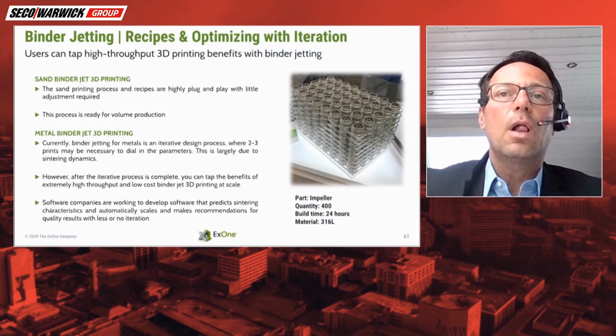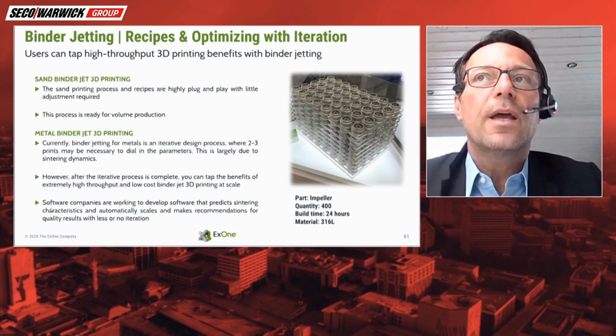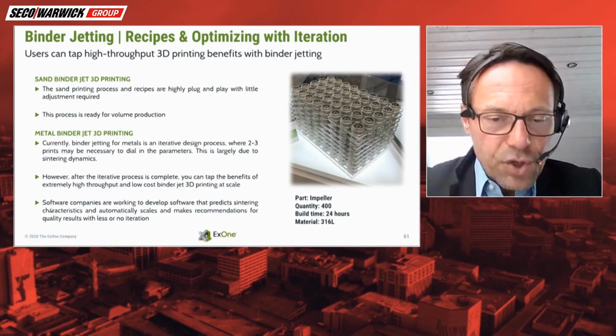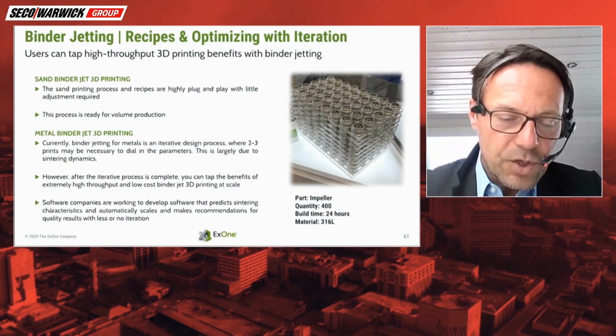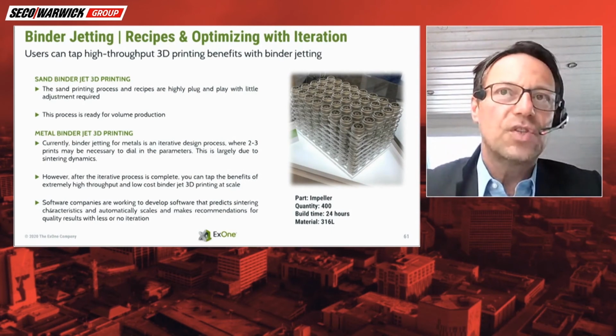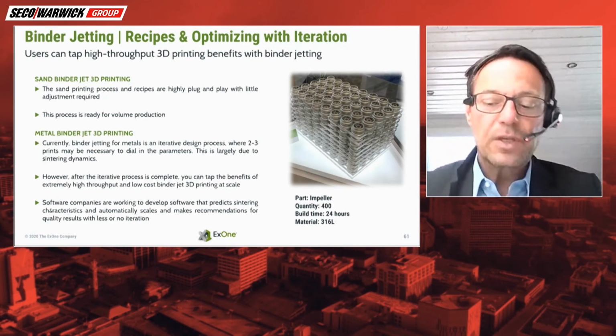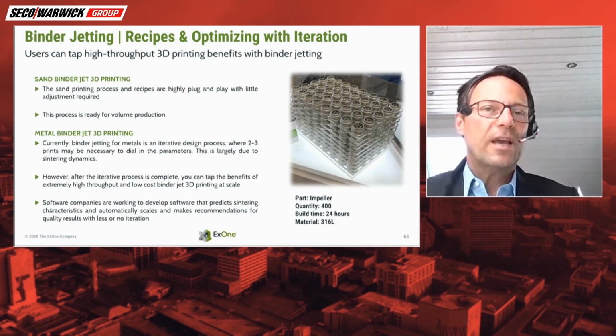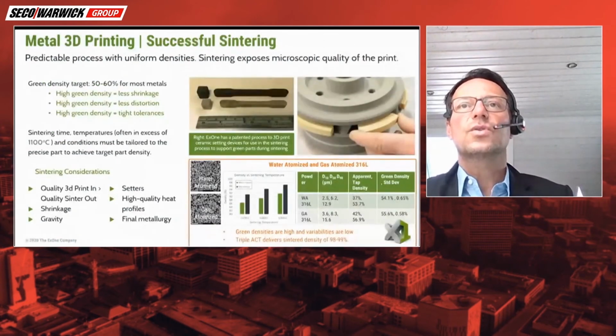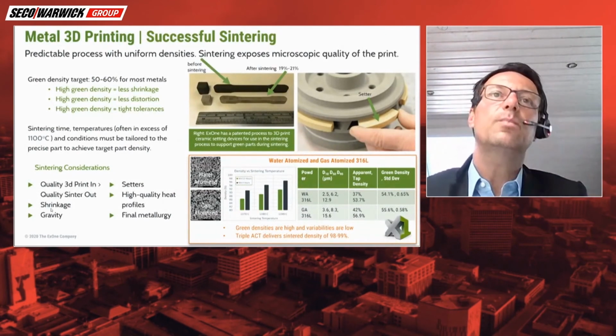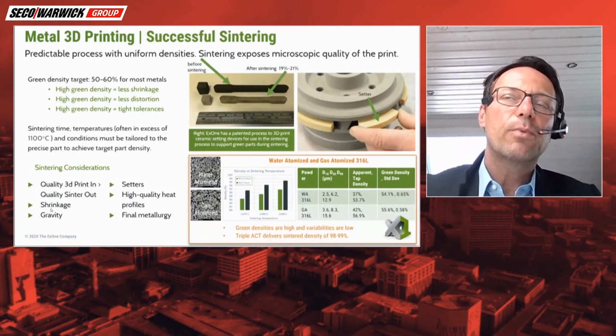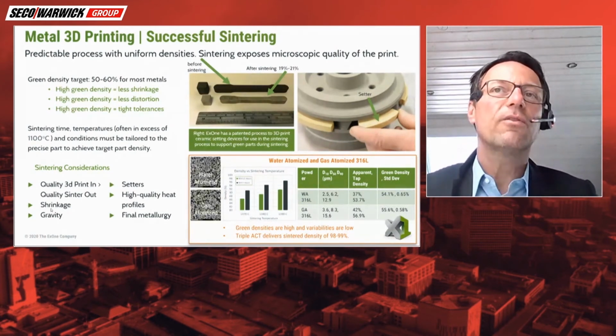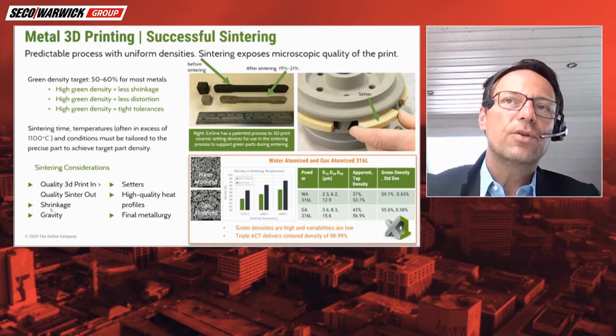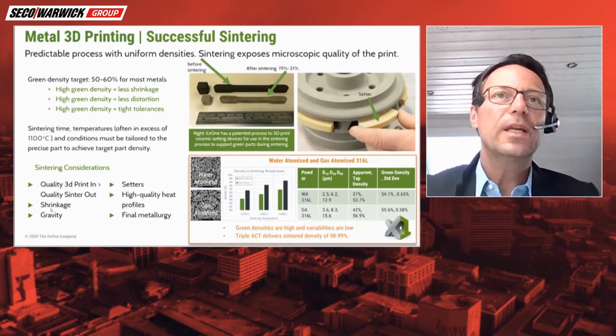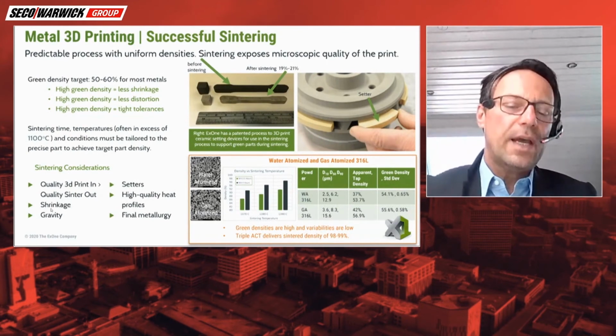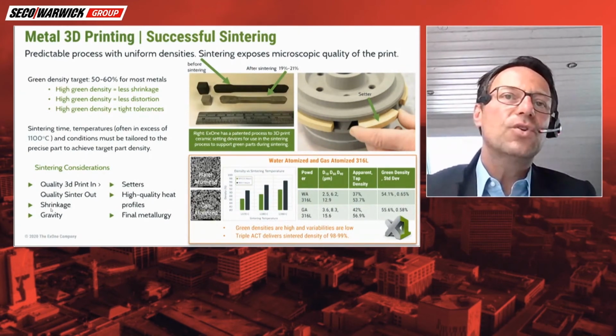If you have gone through all the process steps, there is the shrinkage we mentioned. There is shrinkage happening while we print and then sinter, and that has to be understood because the part is not ready as we have printed it. We go through the sinter process, and yes, there is shrinkage. On that picture you see the black bar and the gray bar. This shows how much shrinkage you're going to face in that process. That makes you think about what is important: I need to redesign in a proper way, and I need to consider the shrinkage.